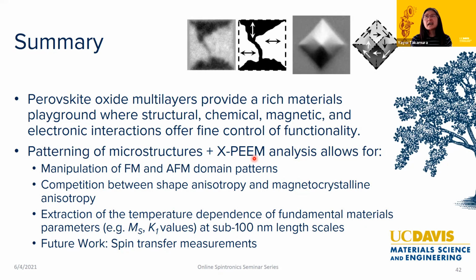In your case, it's all LSMO, just different strain states, so you would still be looking at manganese. You would get the strongest signal from the top part of the sample, but you would not be able to eliminate what the rest of the film is doing, so it would be a combined effect, but it decays exponentially as you go deeper. You would get the strongest signal from that 2 nanometer layer. So that's fine, you just have to count longer. You might have to count 15 seconds per condition for one of my samples, but you might need to increase the count time to maybe 60 seconds per image to improve the image quality. But that's fine.